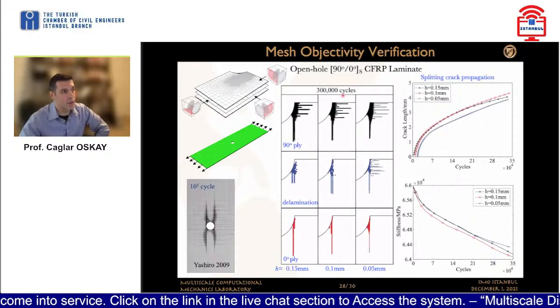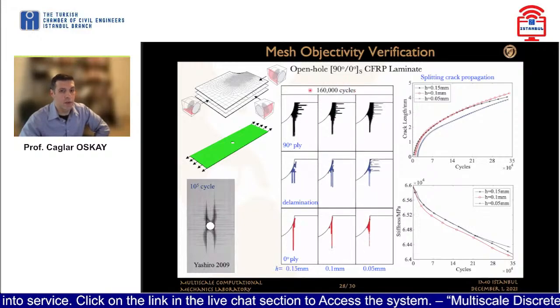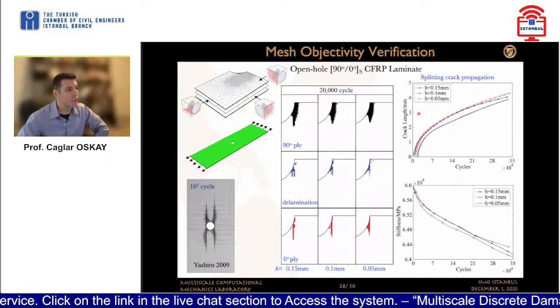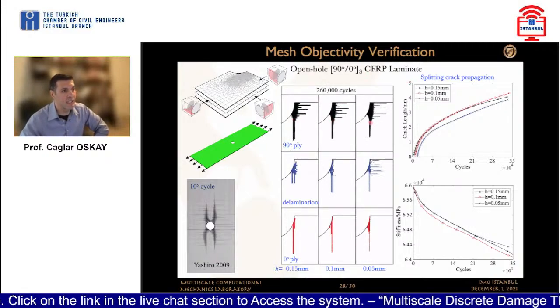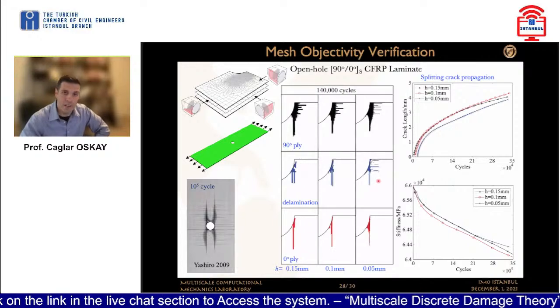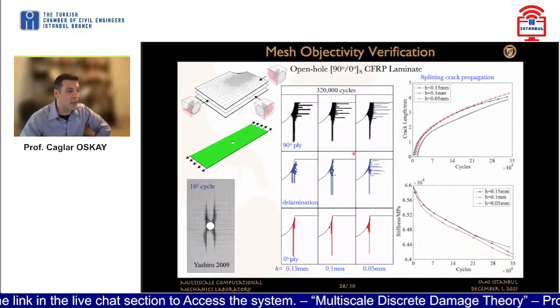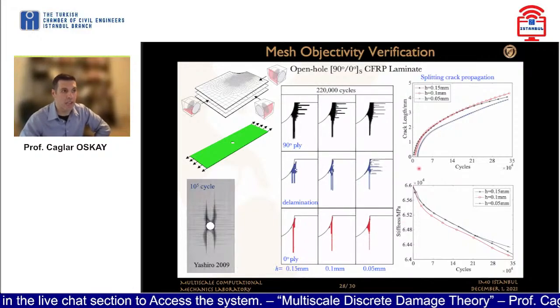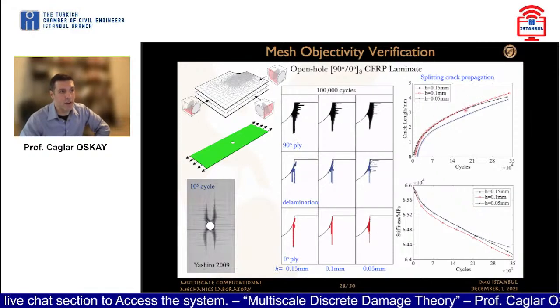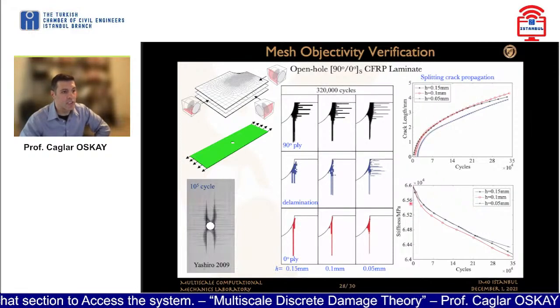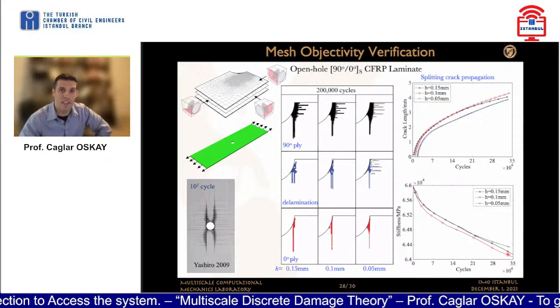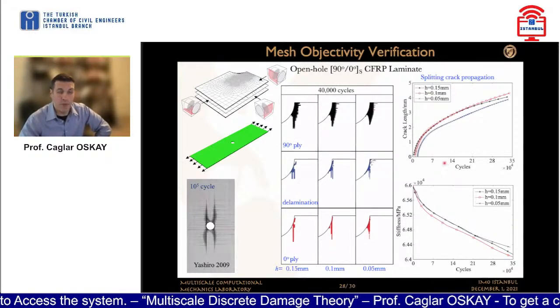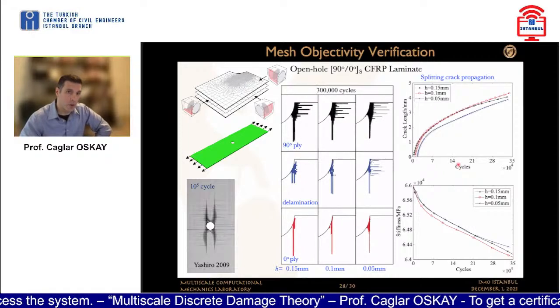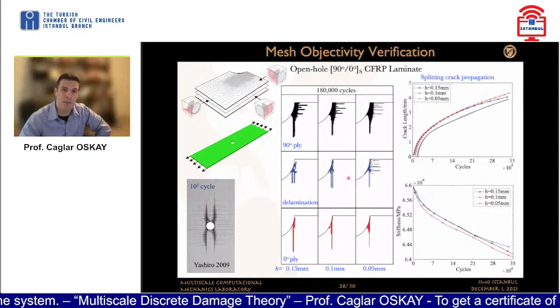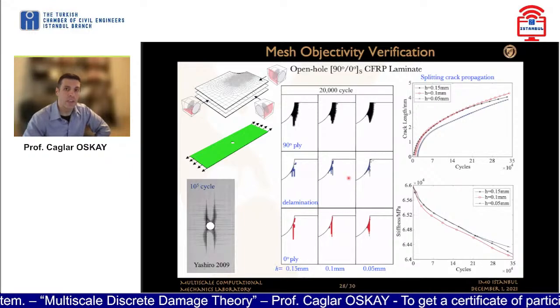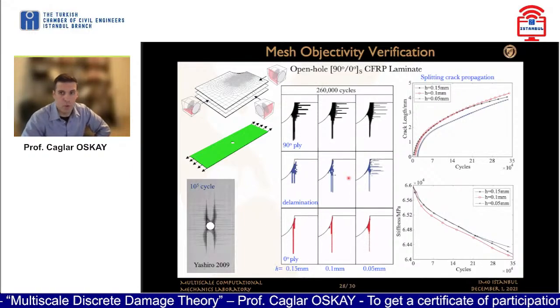As you can see here, we're going in the order of around 320,000 load cycles. And what we're seeing is that the damage patterns are very similar to each other, regardless of the mesh density that we select. And also the specific crack growth and stiffness reductions are quite consistent with each other. I did not even plot the case of what you get if you don't use damage regularization, because you see immediate failure if you do not incorporate the regularization approach that we proposed.